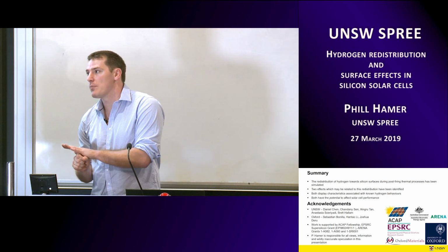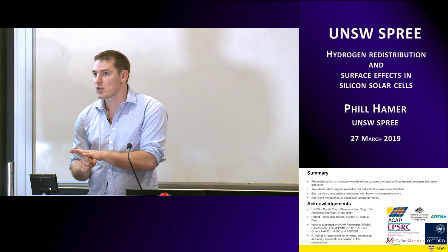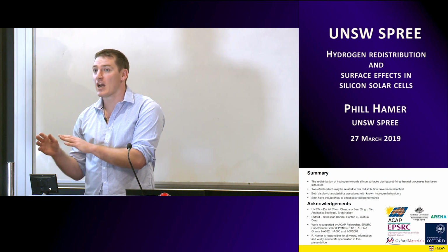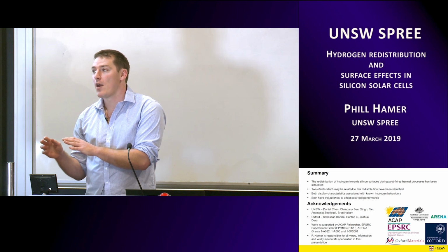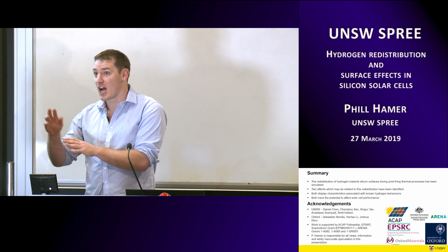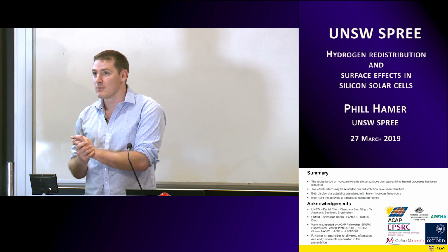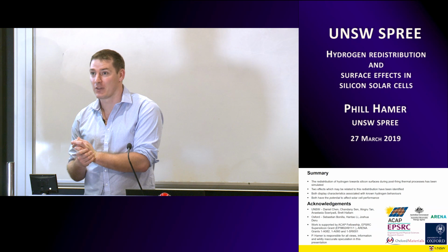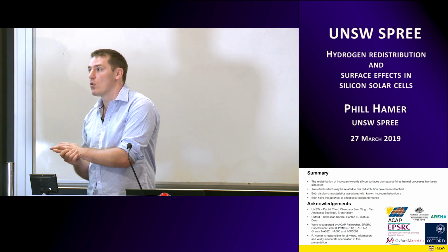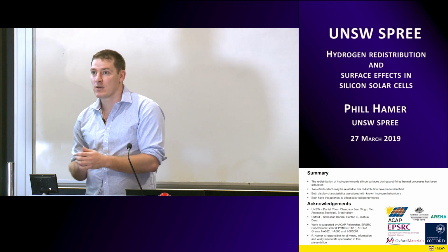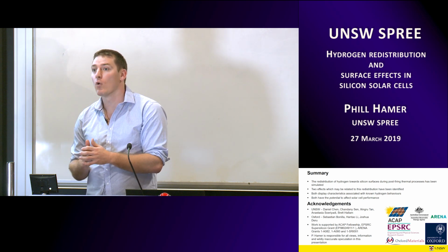My personal opinion is that it's unlikely. So in terms of we can see that hydrogen will deactivate phosphorus. That happens. But to significantly deactivate a large proportion of the phosphorus near that contact would require more hydrogen than I expect to be there. Let's put it that way. I think it's more likely it's actually going to passivate the interface states. But again, a CV measurement, once we have the structures, would tell us more there.